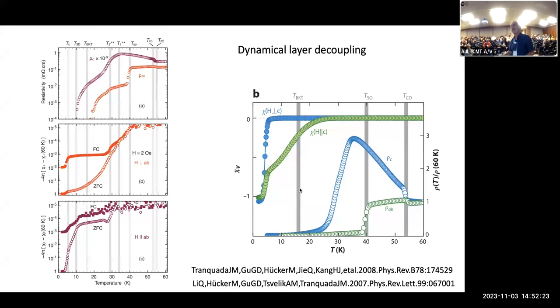Here's these same things on a logarithmic plot. You can see that the resistance doesn't really quite go to 0 here. It has some long tail. It's dropping by many orders of magnitude. So this is something that's almost superconducting, not quite. And the C-axis resistivity goes to 0 at some much lower temperature. So it goes to 0 at 16 or 18 Kelvin. Well, it goes below measurable at some point. You can fit this to a Kosterlitz-Thouless form if you want, and then you can extrapolate to where it goes to 0. You know, if you ask me, I don't think it goes to 0. Can't make a consistent theory if it goes to 0, but it at least gets very small. So it's, you know, more or less superconducting.